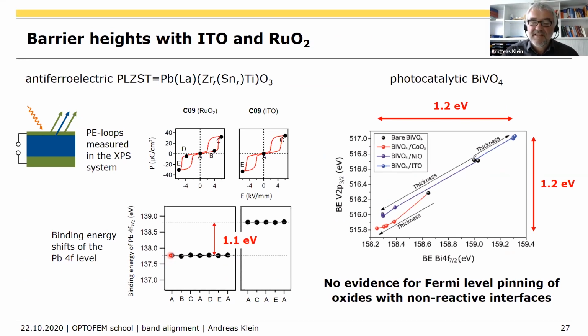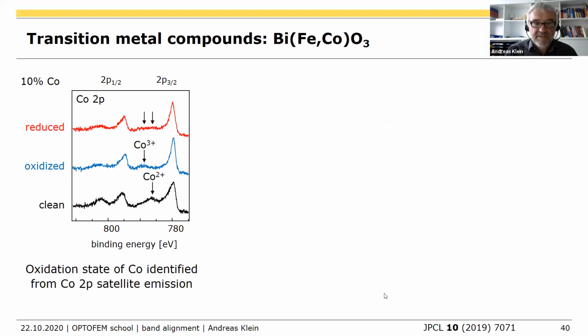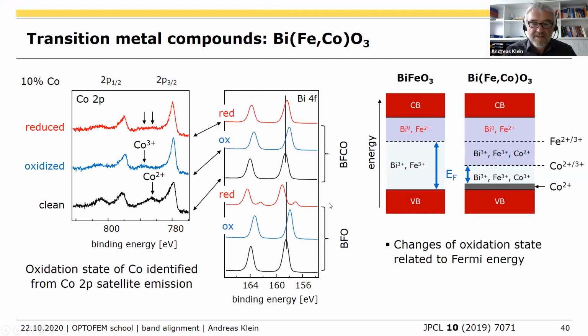But this would not lead to a reduction of the material. That's another thing, because what we saw with the bismuth ferrite is that this reduction would not have been induced by the polarization. It's just an electrochemical process, which tells us that it's really the Fermi energy which is changing. And we see in principle very similar effects with non-ferroelectric materials. So we have no reason to believe that this is caused by the polarization. But of course, it would be nice to check that separately.